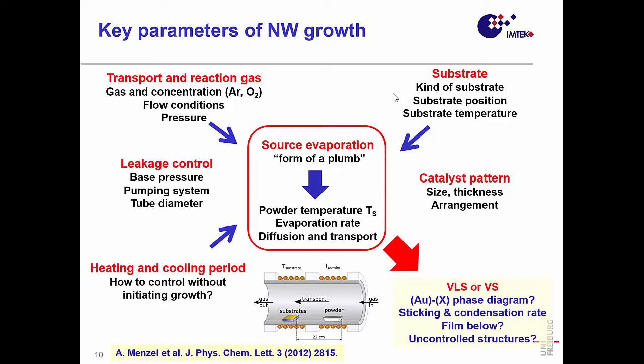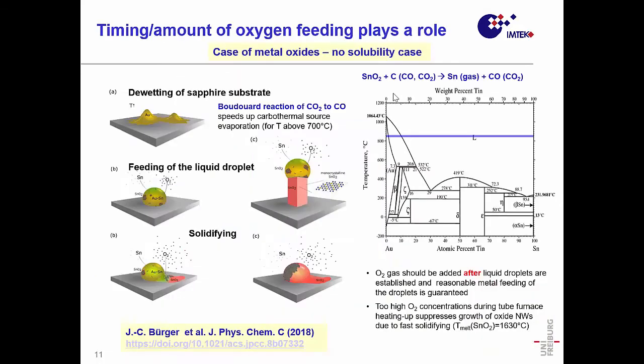So that's very important. If you want to have this VLS growth, what you need actually, and some people forget that, is you have to have a phase diagram. Coming from material science, you know that. So you have a phase diagram between the metal catalyst, which is gold in this case, and the material you want to alloy, you want to grow out of this liquid alloy droplet. And if you look in literature, what you will see is that actually an oxide doesn't have such a phase diagram.